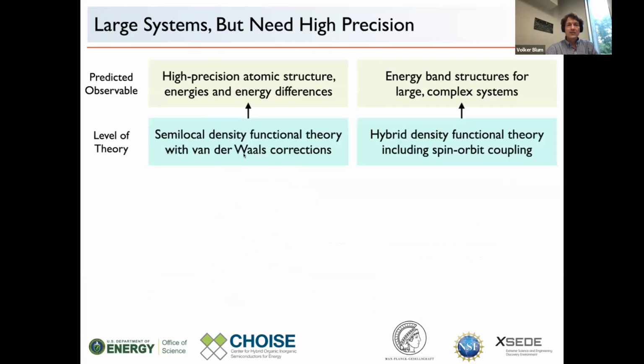And for this talk, it turns out that semi-local DFT, so PBE, with the Tkatchenko-Scheffler van der Waals correction, has actually been good enough for the perovskite work that we've done. Although we know we could do better, right? We could use any of the other methods as well. This carried us quite far in comparison to X-ray diffraction structures in particular. And then for energy band structures to get energy levels right, we've actually been very successful, even for the very large systems, with hybrid density functional theory.